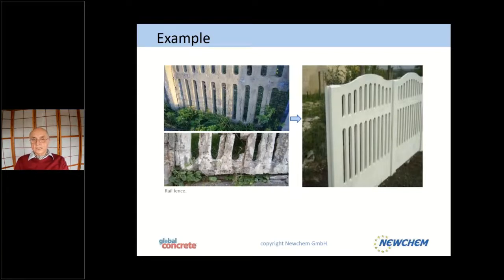First of all, we eliminated the rebars. We made a very high performance concrete. We used some glass fibers and some classified fly ash, which means that we take out the coarser particles of the fly ash and not the fines, giving a very good flow and a good surface. And these panels now can be put in place by 2 persons. And we want it because it's a much slimmer part and a much more lightweight part than the original material.